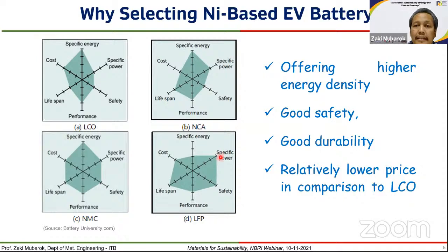The first reason: nickel-based EV battery offers higher energy density. You can see here NMC and NCA, two nickel-based battery types, offer specific energy or energy density which is higher than, for instance, lithium ferrophosphate battery type for EV. It also has good safety, good durability, and relatively lower price in comparison to LCO. LCO is lithium cobalt oxide, without nickel. And the trend, in order to reduce the price, is that the proportion of nickel in cathode material is increased by lowering the proportion of cobalt.